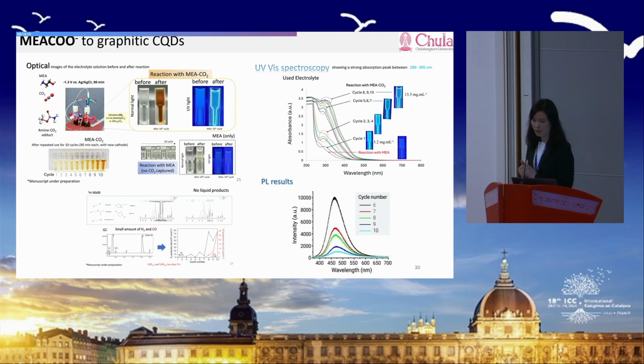This is what we see from the reaction. What we do here: we have an electrochemical cell loaded with MEA, and then we load CO2 in there, put in our electrode, and apply the potential, which is quite low. We applied, I think, minus 1.3 volts versus silver chloride here. After performing a 90-minute reaction, we call that the first run, cycle 1. Then we can even reuse the electrolyte. We replace it with a new electrode, purge more CO2 to capture more CO2. That's cycle 2, and then run again. We do this for 10 cycles.